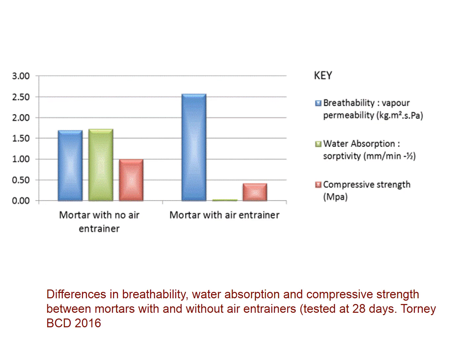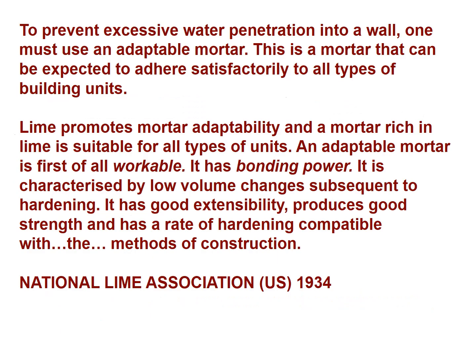Preserving vapor permeability perhaps, but vapor permeability is not an effective mechanism for the drying out of porous fabric, certainly not fabric that is between 12 and 21 inches thick. And this little bit of research by Torney illustrates that the addition of air entrainer all but eliminates capillarity, whilst at the same time increasing redundant vapor permeability.